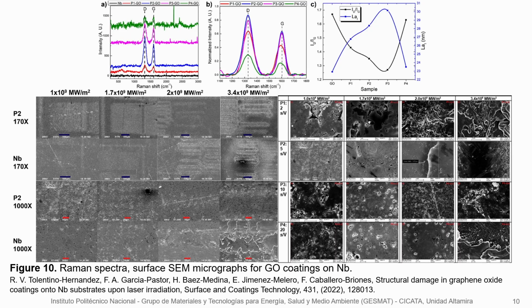This is due to the increase in the thermal conduction of the partially reduced graphene oxide, which gives an economic advantage over graphene coatings synthesized by CVD, since electrophoretically deposited graphene oxide coatings can be reduced by some methods, like thermally or chemically, and can be homogeneously obtained on the whole metal surface, giving the possibility of obtaining graphene oxide coatings at an industrial scale approximation.